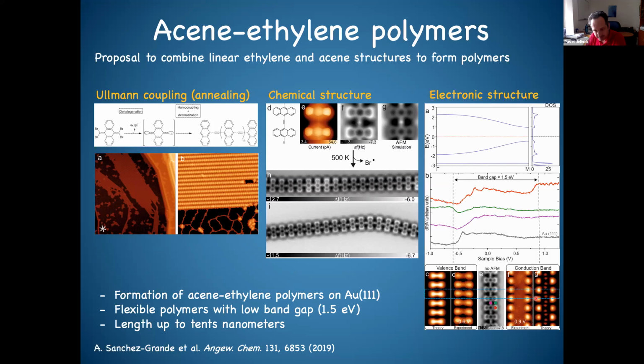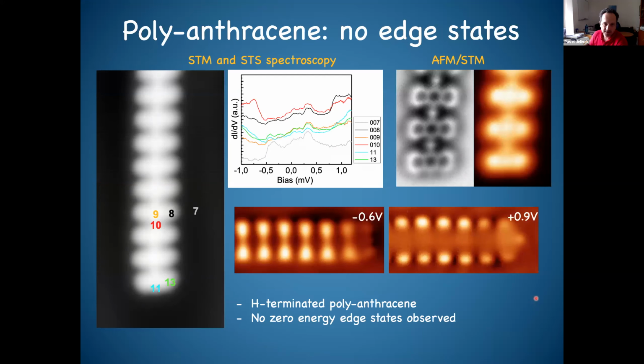Now we have a first system which we said is topologically trivial, so it means that this system should not feature any end state. So now let's have a look at the end of one of these polymers, which is perfectly terminated with a single hydrogen, as it should be. And indeed, when you do this spectroscopy at the edge, you will find that there is no state present at zero bias or low bias at the ends. We only see contrast which corresponds to the conduction and valence band.